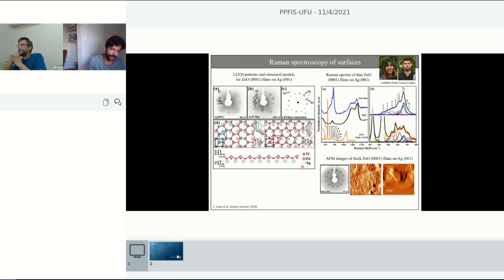So then in this instrumentation branch, I have two examples here to show you what we do. We are going to see through the presentation some of these examples. These are zinc oxide films that are very important for their electronic properties, and then we perform characterization of their structure. So then we can propose these structural models based on a LEED pattern. LEED, for those that don't know, is low energy electron diffraction, where we bombard the surface with low energy electrons, and then we see the diffraction pattern that originates from these films. And from this pattern, we can judge which kind of structure we may have.